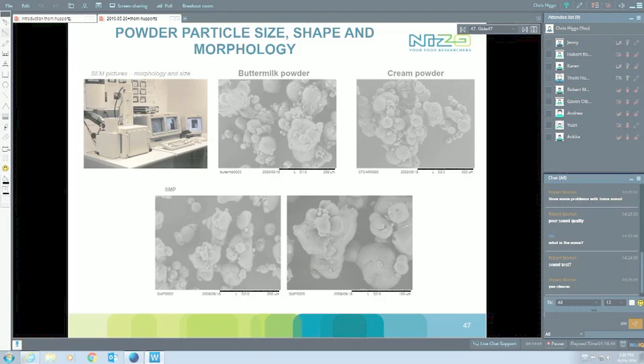Microscopy is a fantastic tool to really see, okay, is it agglomerating nicely? Also, is it just powder particles sticking together, or do I get a lot of fusion? In some cases you see that it's not particles sticking together anymore, but it gets one big core of a particle, and it seems like a lot of droplets have agglomerated. And from that perspective, that will give you poor solution. So it gives you great insights to really put them under the microscope like that.